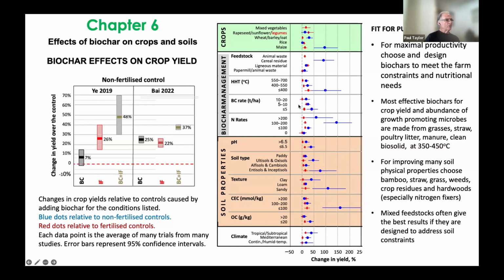And similar things, if you compare it with fertilized controls, those are the red dots, they tend to follow the same trend, but obviously biochar has a much bigger yield effect in unfertilized soils. So the important thing is for maximal productivity and profitability, choose and design a biochar to meet the farm constraints and nutritional needs. And just a couple of key points, the most effective biochars for crop yield and promoting microorganisms are made from grasses, straws, poultry litter, manure, and clean biosolids at relatively low temperatures.